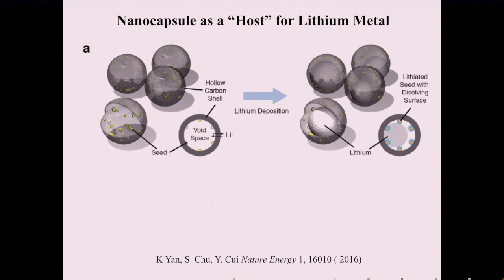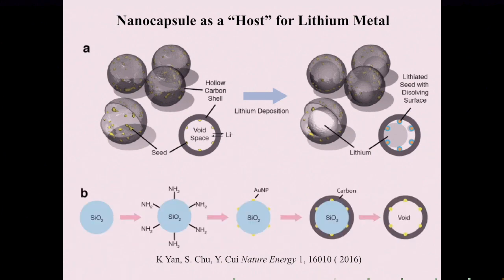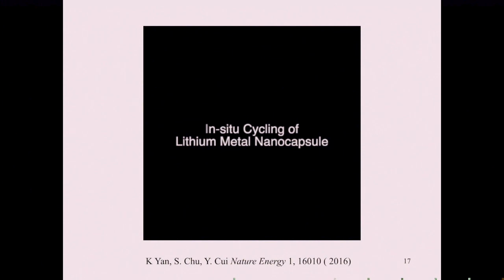If you plate lithium, lithium goes in. And then you can isolate lithium metal from the electrolyte and contain metallic lithium in there. We actually made this structure. Let me show you an in situ electron microscopy video. Here at Stanford, we have these beautiful tools. They're so important. You can charge and discharge the battery inside the electron microscope to see what's happening.